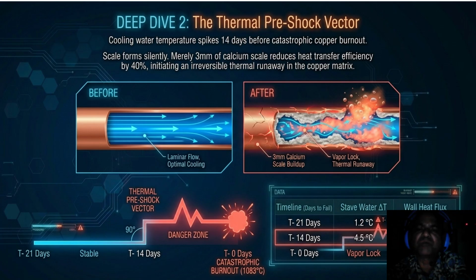Follow the red line on the graph. Notice the spike in the stave water temperature 14 days before the actual failure. We call this the thermal pre-shock. Merely 3 millimeters of scale reduces heat transfer efficiency by 40%, initiating an irreversible thermal runaway. By the time you hit T minus 0 days, the copper matrix reaches 1083 degrees and melts. The so what factor here is your lead time. You have a 14-day window where the data is screaming at you that a burnout is coming. So if you are not monitoring the delta T and heat flux, you are just waiting for the explosion.